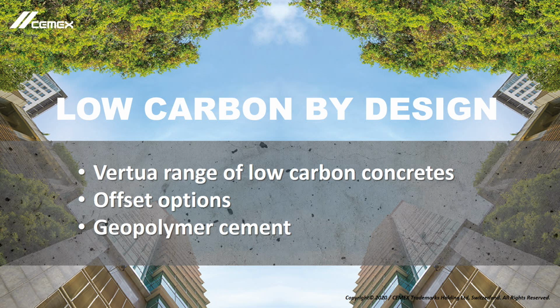This is one issue. Another issue is, when Gus was just talking about adding fiber to increase the tensile property, my understanding is that if you add some fiber into this kind of material, it could have a potential hazard because the fiber diameter is quite small, so the industry may hesitate to use these. That's my opinion, because I know in China normally we're not allowed to add fiber into the cement or concrete, because it could be a potential hazard for the worker, like asbestos in the future. So we just discussed this problem, where they have added some kind of glass fiber or carbon fiber into the cement. Thank you.